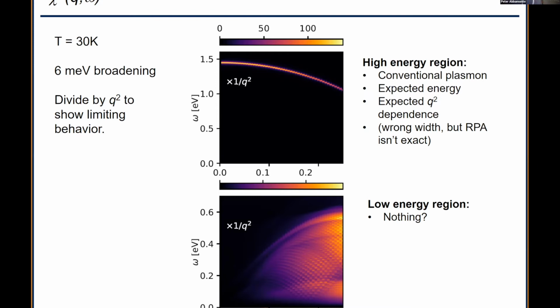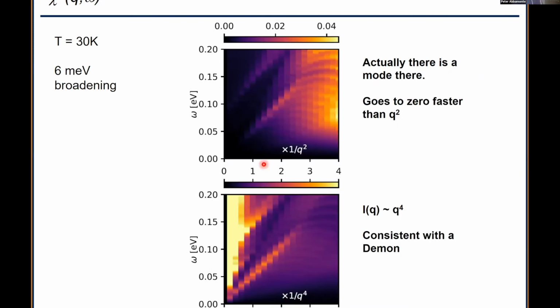But wait just a second. You have to look really close. If you look really close, there's a mode there, and its dispersion is linear. But it seems to vanish as q goes to 0 in the calculation. Now, why is that? The reason is that this is chi double prime divided by q squared. But if it's a demon, its spectral weight has to go faster than q squared because it's neutral. So if you multiply by 1 over q to the 4th, its intensity goes to a constant.